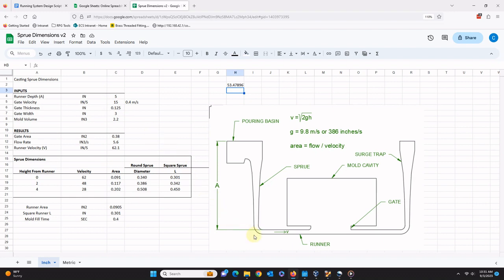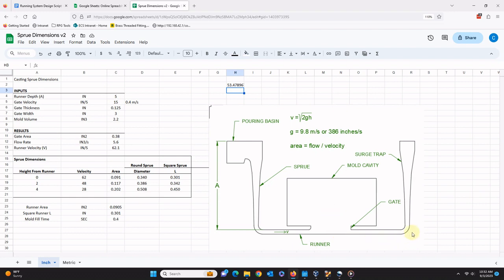An astute viewer may note that these two principles come into conflict at the point where metal transitions from the runner to the gate. In this design, the speed of the metal in the runner is 62 inches per second or approximately 1.5 meters per second. This is much higher than the critical speed and would make a mess if the metal were to enter the mold cavity directly. Even if the runner were widened at this point, the momentum of the metal in the runner would cause it to break up into a jet rather than spontaneously slowing down. Therefore, a surge trap is used to capture the initial flow of metal, gradually build up pressure, and then divert the flow in a right angle at a lower speed. There are different forms of surge traps. This is a simple one that works for molds with vertical parting planes and can be seen in some of my other videos.